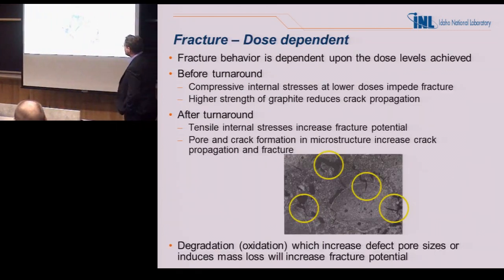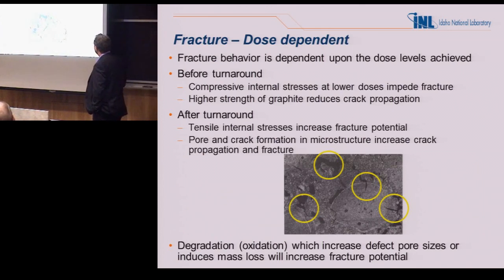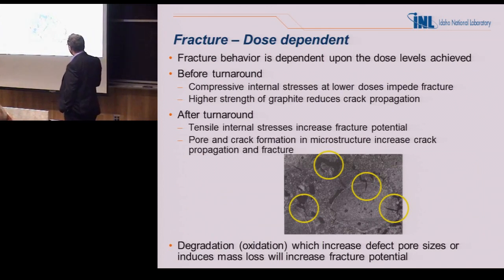Okay. Fracture, again, is dose dependent. It's dependent upon the dose level achieved before turnaround. Everything's compressive. You don't propagate cracks under compression. All you mechanics folks know that. And so at the lower doses, basically it impedes fracture. It also gets stronger, so again, you're getting less and less crack propagation.